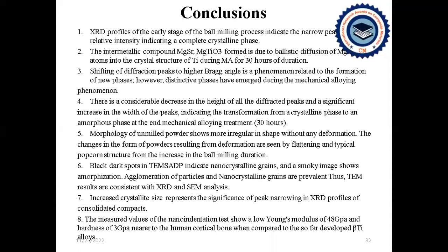And the measured values of the nanoindentation test show a low Young's modulus of around 48 gigapascal and hardness around 3 gigapascal, which is nearer to human cortical bone when compared to the beta titanium alloys developed so far. So in our present investigation, the developed titanium magnesium strontium alloy, which possesses low Young's modulus, is favorable for biomedical implant application.